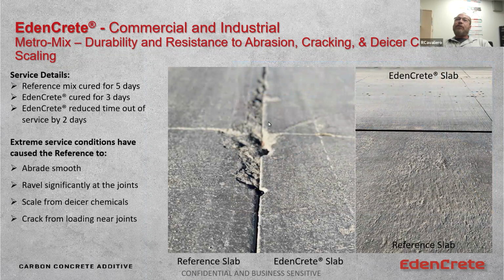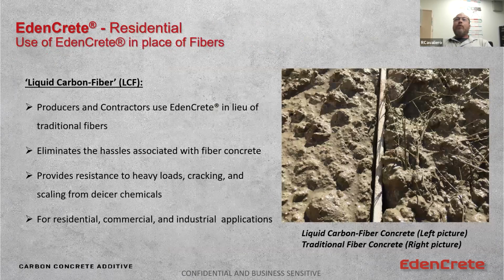Like I said, we are not indestructible, but this is a shared joint. This is EdenCrete on the right. This is not EdenCrete on the left. And some event has occurred that's caused that level of damage on that one and not the EdenCrete. And you can see similar up here on this one right here. So Hector, we went from there and we basically developed a line of mixes where we use EdenCrete in place of fibers